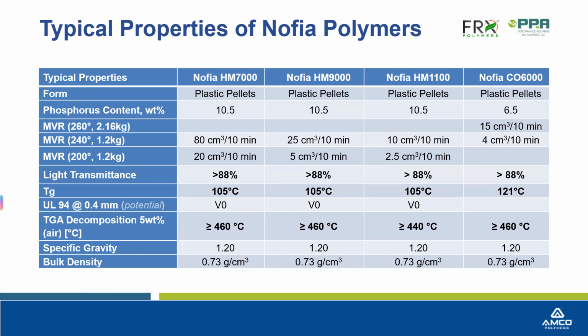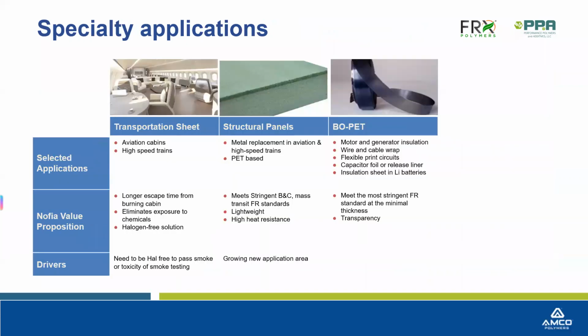This is the transparent material with a light transmission of 88%, not very different from polycarbonate. It has a Tg of 105 degrees C, which is a high Tg for a flame retardant additive. And then the copolymer that's used as a blend in polycarbonate applications has a higher Tg, 121 degrees C. The material also has very good thermal decomposition level, well over 400 degrees C before you see any loss of molecular weight. So those are the key characteristics. Otherwise, melt viscosity is based on molecular weight. So I would like to highlight a few of the applications that a polymeric non-halogenated flame retardant enabled.